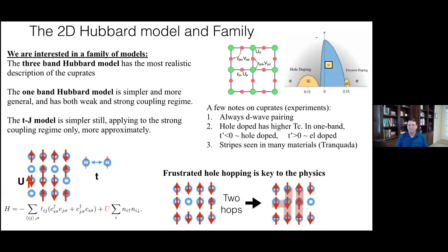There are two different regimes where you dope it with holes or dope it with electrons. In this upper right diagram, the hole doping is on the left, and that generally gives you a higher Tc. Now, if you map things to the one-band models, then roughly we can take into account the difference between hole doping and electron doping with a t prime.